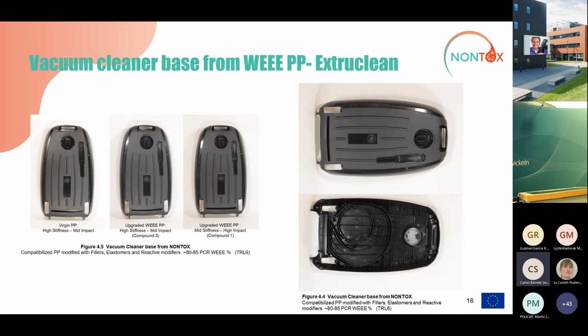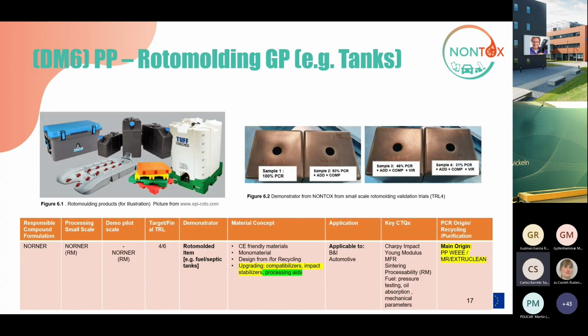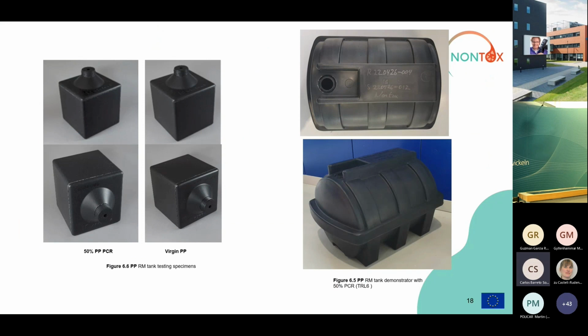Here it was really missing even more powerful fillers to enhance the stiffness, and that could still comply with the topic of design for recycling. This other one was about using polypropylene from WEEE, again, devolatilized by Extruclean. And here we are really proud to share a breakthrough in using this material for rotomolding, enabling this step by some processing aids in a package that was especially developed here, where the sintering was enabled by these additive packages. We successfully advanced in the production of tanks and did some steps towards the validation in the direction of fuel tanks. But in general, the material was proven to be suitable for general purpose rotomolding.